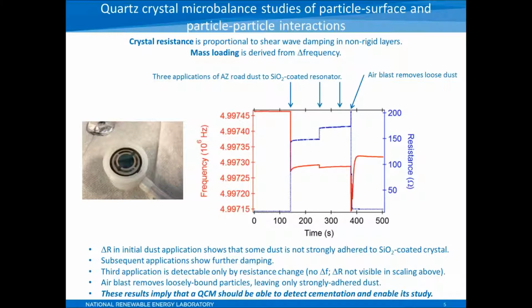We see a decrease in the crystal frequency, and if you make a number of assumptions, you can convert that directly into mass per unit area. But you also see that the crystal resistance increases dramatically. Now, if this had been a thin film of some sort that was rigidly adhered, you would see no change in resistance. So right away we know that this initial application of Arizona road dust is characterized by tightly bound material that causes the drop in the frequency, simply because we've added mass to the resonator. The resonant frequency has decreased, but acoustical losses are occurring at the same time. So that means there's some loosely bound material.